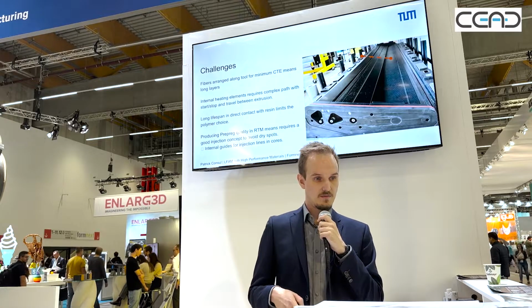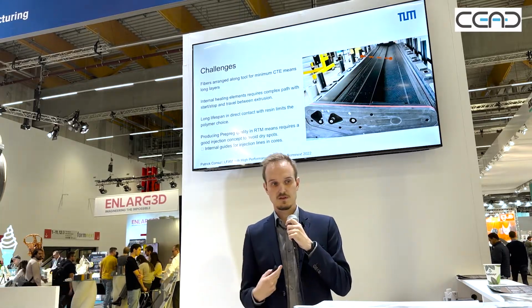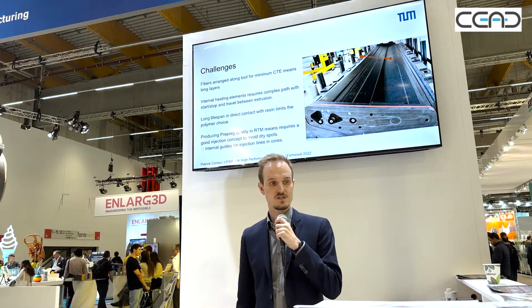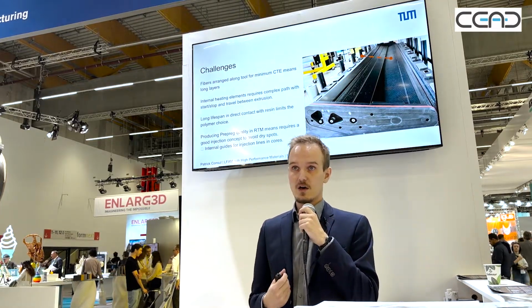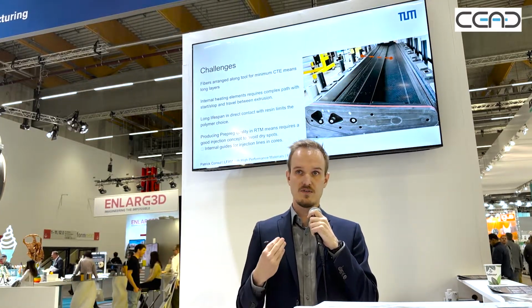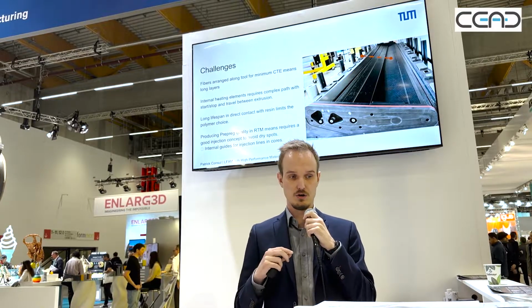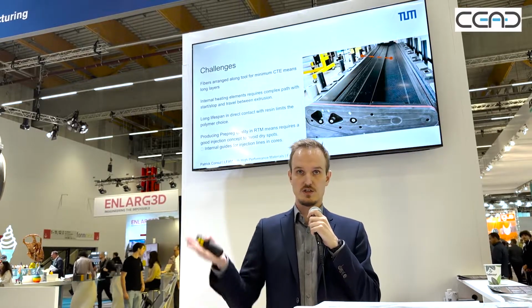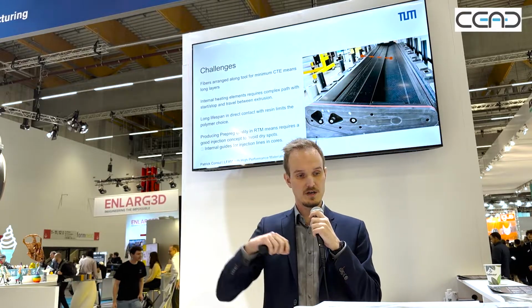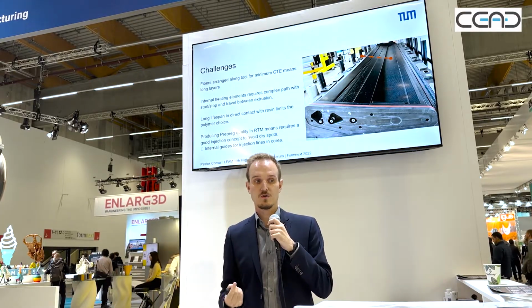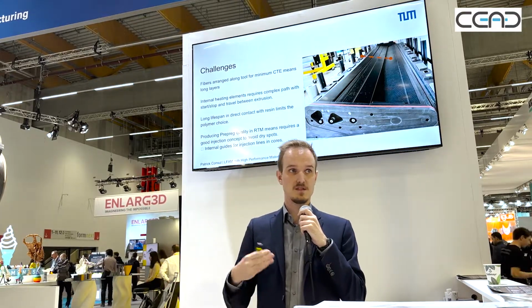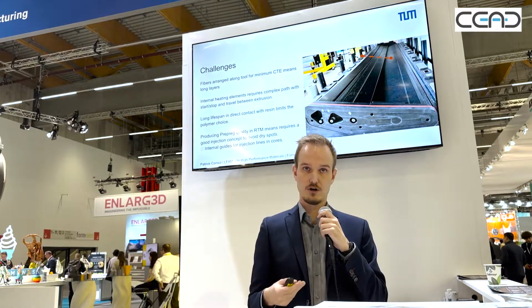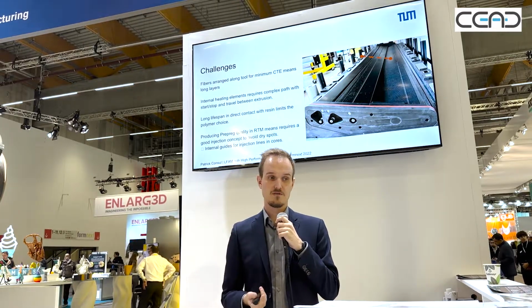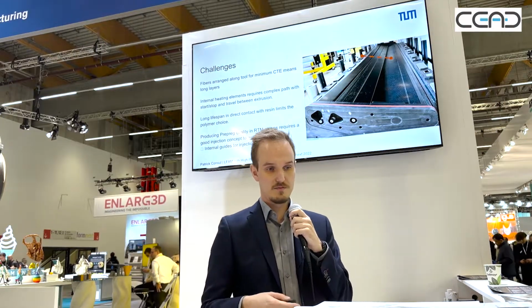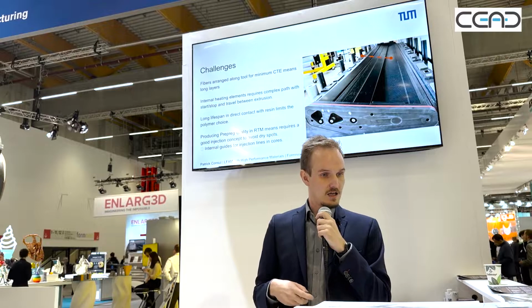And the way we approached these challenges, first the CTE, was we printed it in a way that all the fibers align along the long axis of the print. So we actually printed it standing up and had very long extrusion lines, which in turn also meant that we have very long layer times and the material cools down quite far, which can be difficult for PEEK as it tends to delaminate, but BigFlex found a solution for that.